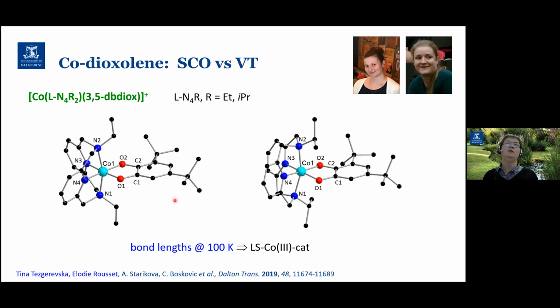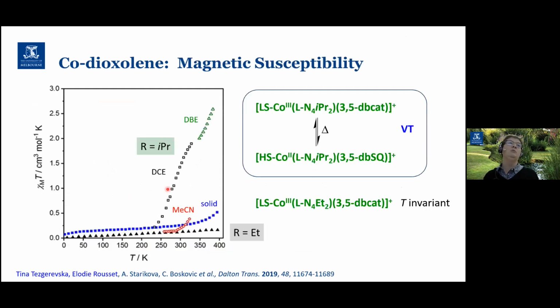So at 100 Kelvin, in both of these complexes, the bond lengths are entirely consistent with low spin cobalt-3. That's the cobalt, oxygen, and nitrogen bond distances, and also the bond distances of the dioxolene ligand, again, very indicative of the redox state of that ligand. So in both cases here, they're in the catechol oxidation state. So when we went to look at magnetic susceptibility measurements, first of all, these black triangles here are the ethyl analog, and essentially that's diamagnetic at all temperatures up to 400 Kelvin. So that's in the low spin cobalt-3, catechol, charge distribution, temperature invariant.